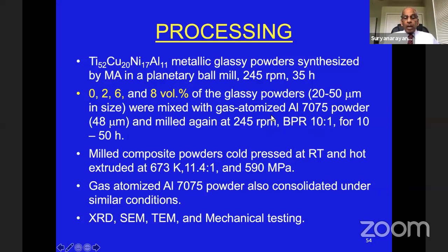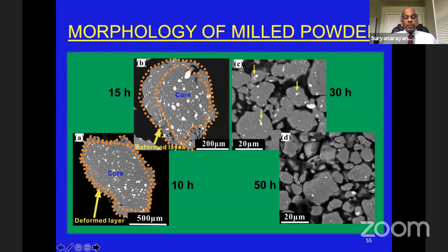And so we took aluminum 7075 powder, added 0, 2, 6, and 8 volume percent of the titanium, copper, nickel, aluminum glassy powder, mechanical alloyed it, and then cold pressed at room temperature and then hot extrusion. Then you have all these different techniques to characterize this material.